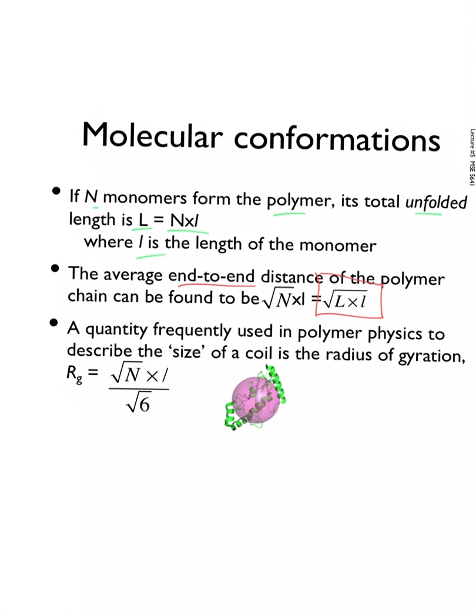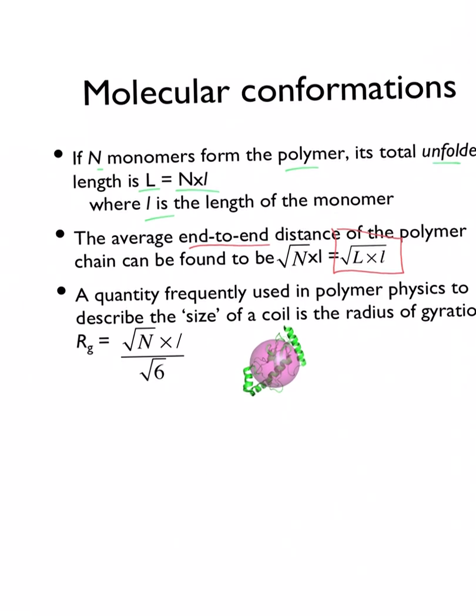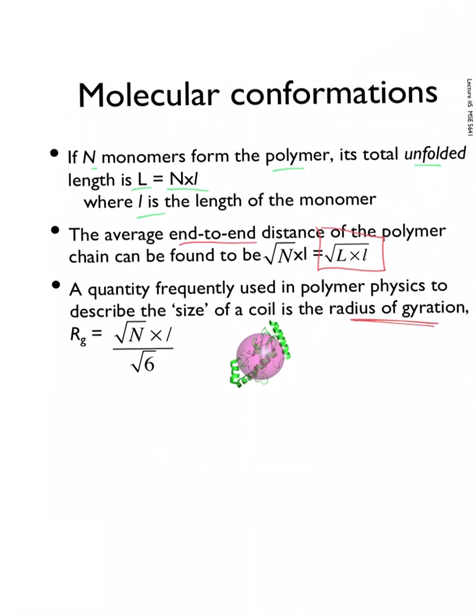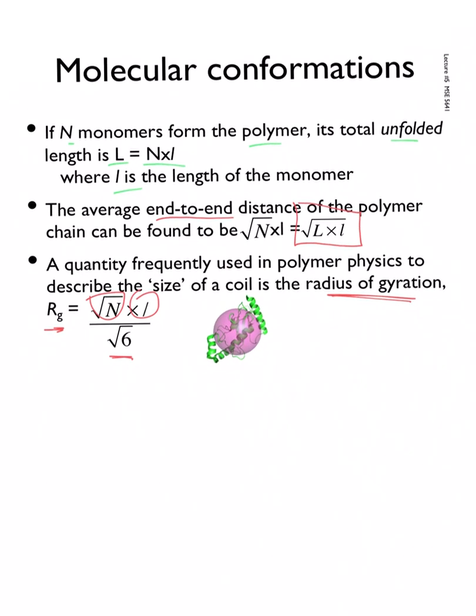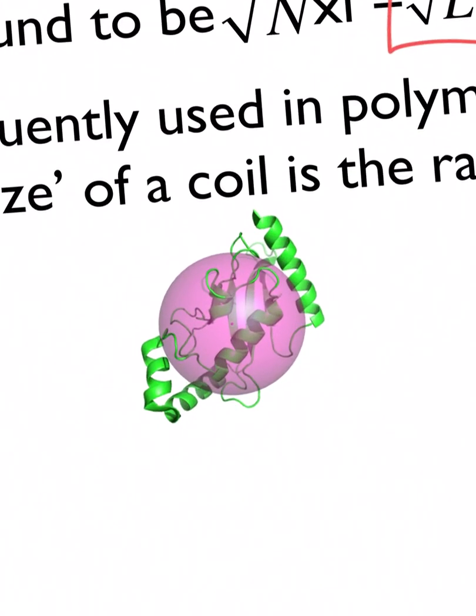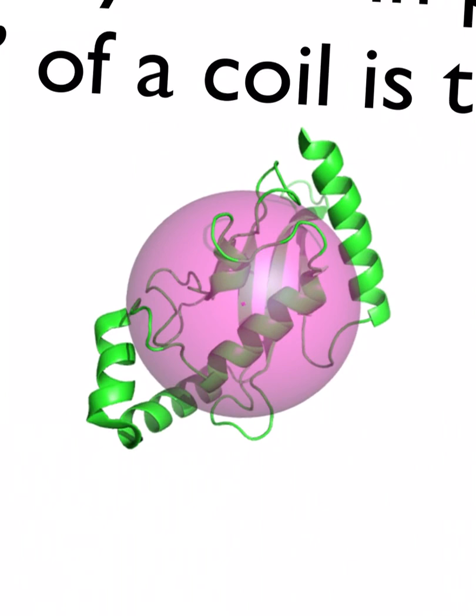But what I really want to talk about is a different term, which is called the radius of gyration, which you saw a minute ago anyway. R sub g is equal to the square root of capital N, the number of monomers, times that length of each monomer divided by the square root of 6. And when we talk about and compute R sub g, this is showing you the radius of gyration for bovine serum albumin, a biological molecule. And that's what you're seeing here. These guys are amino acids that make up that protein. And if we compute the radius of gyration, it's this pink sphere. That's R sub g.